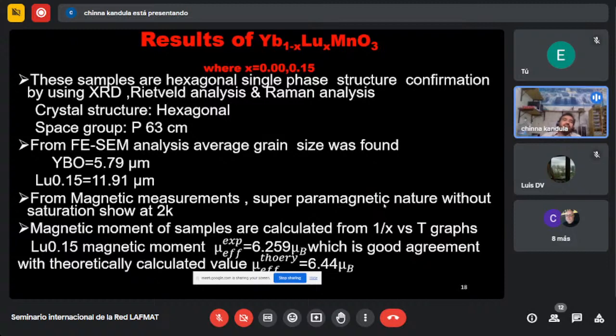From the Rietveld refinement, the sample showed this hexagonal single phase structure, confirmed by XRD and Raman. The structure is hexagonal, and the space group comes to P63cm. From FESEM analysis, the average grain size was found to be higher for the lutetium doped sample compared to the parent compound, because of this doping effect. And I took the M-T measurements. It shows the super paramagnetic nature without saturation at 2 Kelvin.